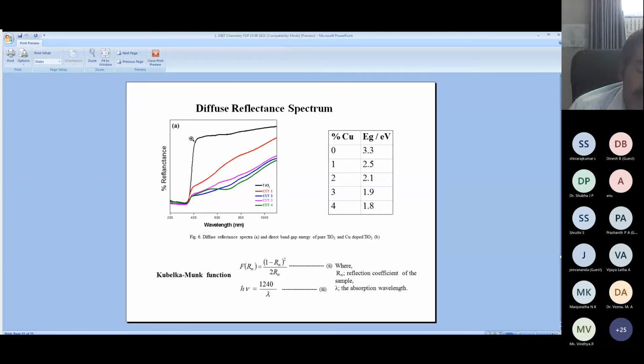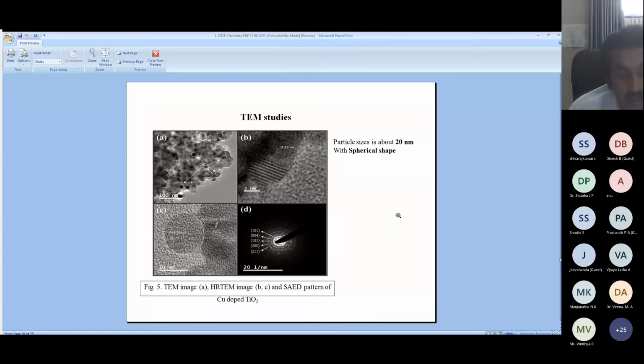Okay, now when we did the optical property and band gap measurement, the report shows that 0% pure TiO2 has a band gap of 3.3. As the percentage of copper increases, the band gap decreases, right? As the band gap decreases, it is a good photocatalytic material. Now, this is the HRTEM pattern for the copper doped TiO2, and the dark spots indicate the presence of copper. At the same time, in the SAED pattern, all the lines are not in the same direction, which indicates that the material is polycrystalline, a group of lines, right? This is the pattern for copper, this is for TiO2, which says the material is polycrystalline.